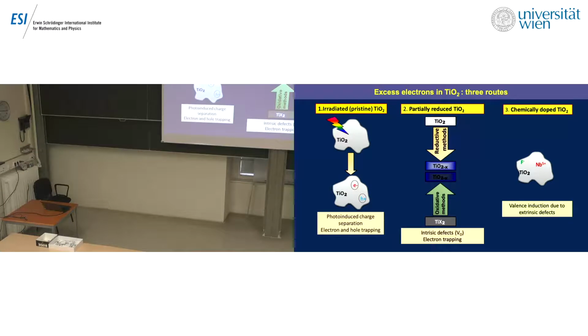As I have shown previously, okay, you can irradiate a system and obtain electrons and holes. Up to now we have considered the hole, but there are other systems, okay, that are reductive methods of annealing, and to reduce the system, these are reducible oxides, and you produce extra electrons in the system, but also oxygen vacancies that perturb the system. Surprisingly, there are also oxidative methods. You can prepare titanium dioxide oxidizing a low valence compound, and also in this case you can obtain imperfect things, a non-stoichiometric oxide.